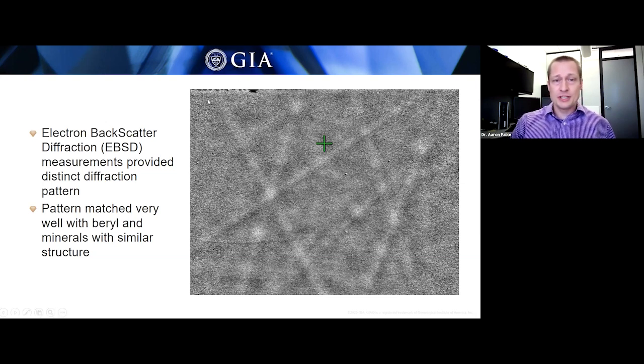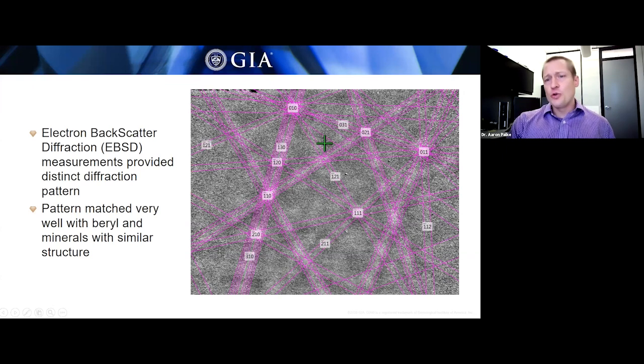And you'll see that here, this is the output of the EBSD measurement. You see these kind of faint lines going through this structure. These are the diffraction lines coming off the material. And what you do with EBSD, you can index those lines against your known reference database. In this case, the closest match was with beryl or other minerals closely associated with beryl, so other beryl group minerals. And so we found, again, this structure is going to be very similar to beryl probably. The Raman spectrum was pretty close to beryl, and the EBSD was pretty close to beryl as well.